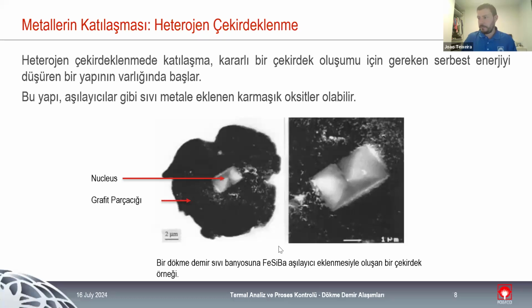And this is basically what we have with heterogeneous nucleation. So we are adding an active element, barium, zirconium, aluminium, calcium, bismuth, lanthanum, whichever we are adding. There are some differences that we are going to discuss later on, but we are adding a substrate for the nucleation to happen. And it is basically what we have in this image. We have a substrate and the nucleation happens around the substrate. The graphite particles grow around the stable nuclei that we gave to the liquid metal.